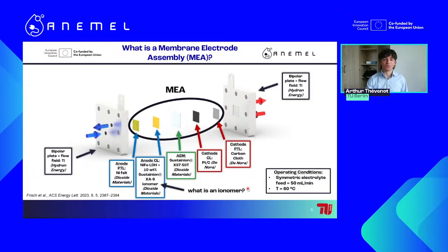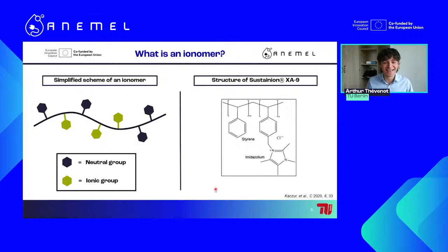So what exactly is this ionomer that I just described? Well, it's a very important component for this study. It's actually the central component of this study. An ionomer is a polymer. A polymer is a very long molecule, like a chain, with repeating building blocks, these repeating units. The difference between an ionomer and a simple polymer is that an ionomer has mostly neutral groups, neutrally charged groups, but also ionic groups, so charged groups, either positively or negatively. In our situation, with this Sustainion XA-9 ionomer, we have as a neutral group this styrene group over here, and as an ionic group this one, which includes an imidazolium group, with this positive charge that we see right here.